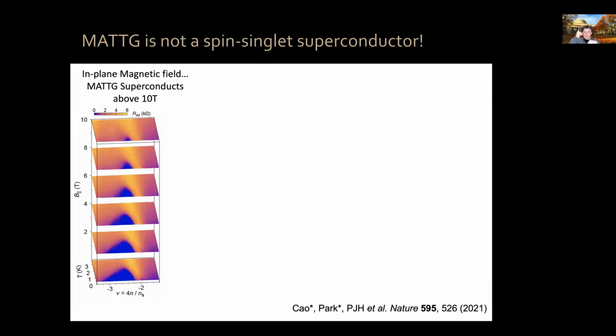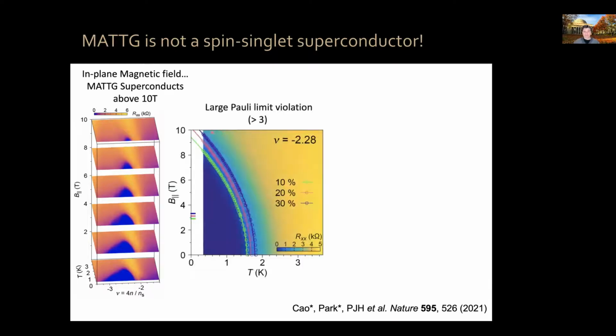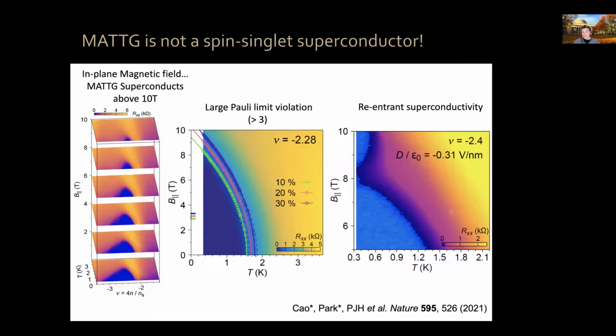Usually a spin singlet superconductor would disappear at a certain magnetic field called the Pauli limit. But it turns out that in magic angle twisted tri-layer graphene, the system superconducts way above the Pauli limit. These data points represent here the Pauli limit for different resistance thresholds. And this dark blue here, which means superconductivity, shows that the system is superconducting up to magnetic fields much, much larger, over a factor of 3 larger than the Pauli limit, okay? Not only that, but in some parameter regimes, we can actually kill superconductivity, and then superconductivity reappears at high magnetic field. This is known as reentrant superconductivity, and it typically only occurs in very exotic type of ferromagnetic or spin triplet superconductors, okay? So magic angle twisted graphene is very likely not a spin singlet superconductor.